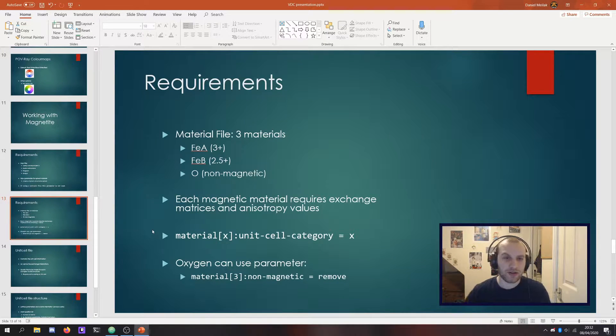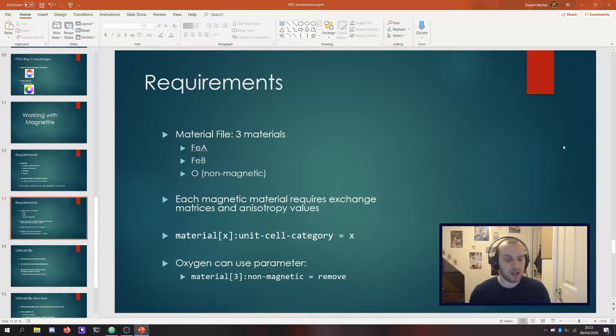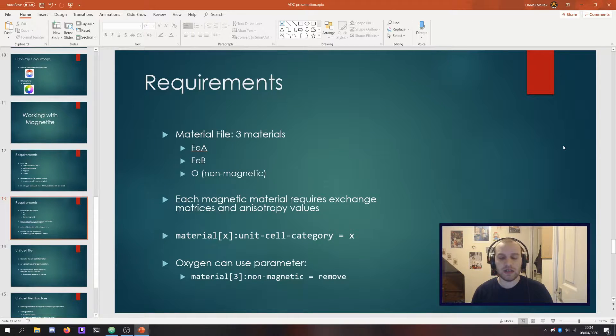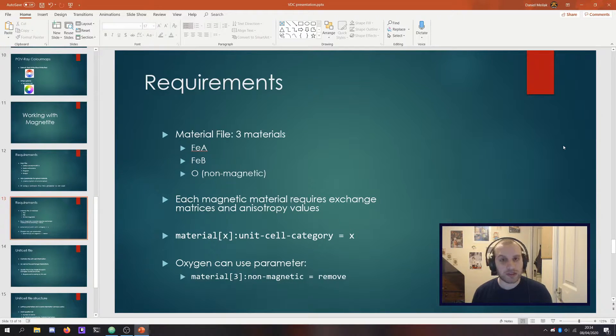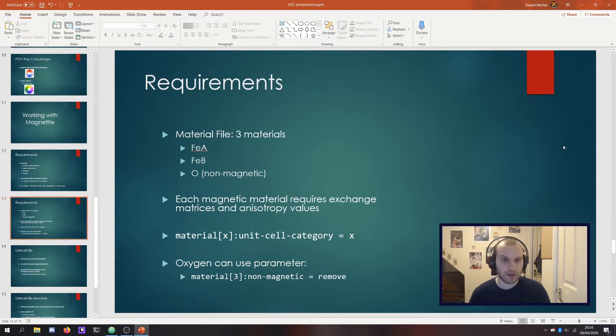You might want to compare this to the material file provided for cobalt in the Vampire source — you'll see that there's a lot more things going on here. We've got three materials: an FeA sublattice, an FeB sublattice, and oxygen. Magnetite is a ferrimagnet. You've got the A sites, of which there are eight iron atoms along the easy axis — let's say positive [1,1,1] — and then you've got 16 atoms of iron on the B sites, which are facing the opposite direction, anti-parallel. Because there's twice the number of FeB sites, this material can behave a lot like a ferromagnet, which is what people initially thought it was. You've also got oxygen completely dispersed across the material — there are 32 atoms of oxygen in the unit cell — but it's non-magnetic, so for the most part we don't really have to worry about it.